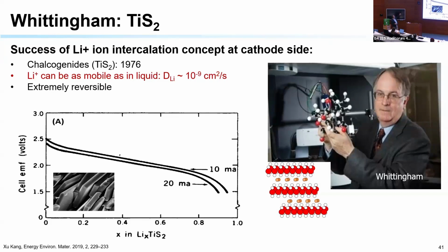So this gentleman showed that lithium can go in and out in this titanium disulfide at a very high mobility. And then he showed that with a voltage, he can actually take the lithium in and out. This X here is the amount of lithium you put in titanium disulfide, okay? So you're changing the composition in and out, forming a solid solution. So he showed that in 1976. And in fact, the first lithium-ion battery that I showed you earlier and said it's still working was done by him.